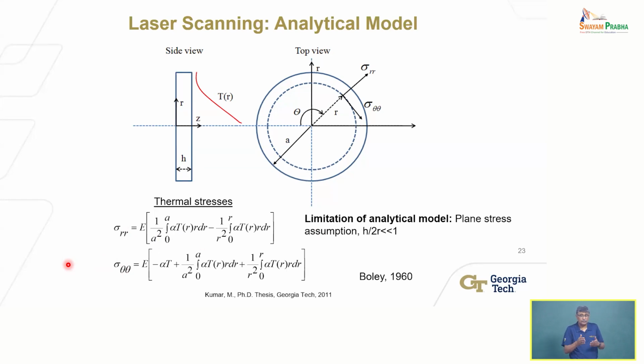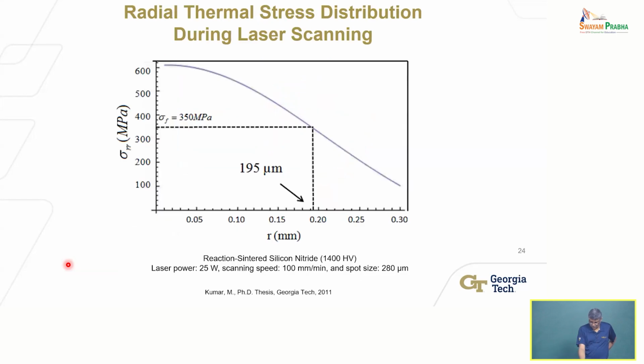Whichever one is sufficiently high, that is, exceeds the known fracture strength of the ceramic, then you'll generate cracks, right? That's the idea. So this shows you using that analytical model, in this case a reaction-sintered silicon nitride, which is a ceramic, okay?